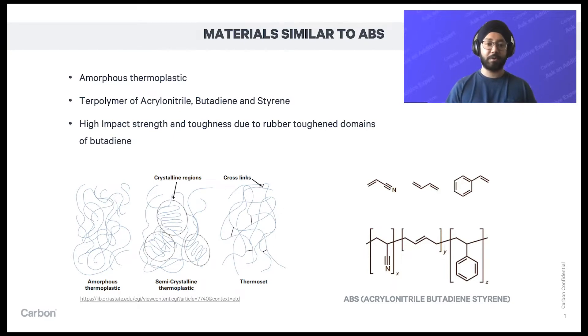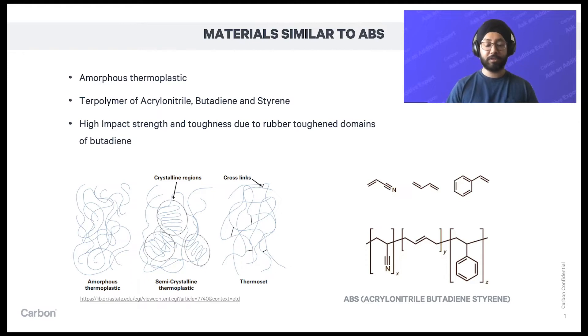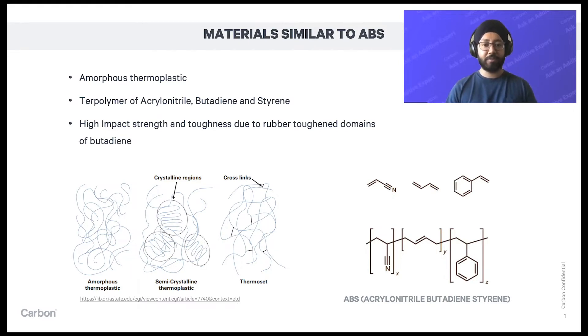Coming back to understanding ABS more — it's a terpolymer, meaning it's a mixture of three different monomers: acrylonitrile, butadiene, and styrene. On the slide deck, you can see that acrylonitrile makes it slightly more polar and lets everything mix up pretty well. You have styrene as the component which gives it rigidity, makes it more stiff, and gives it very high thermal performance resistance. The more styrene in the formulation, the stronger and the higher temperatures it can withstand.